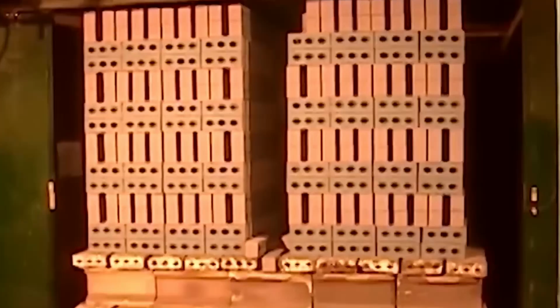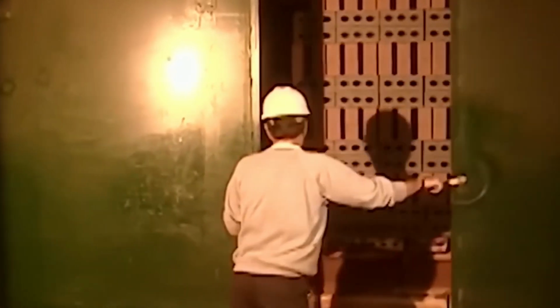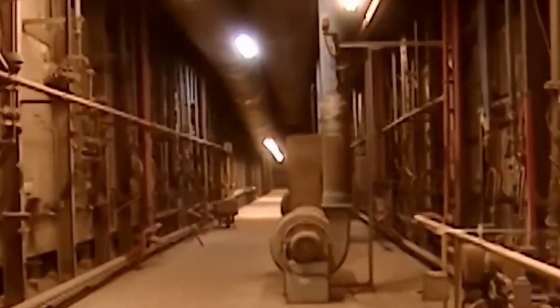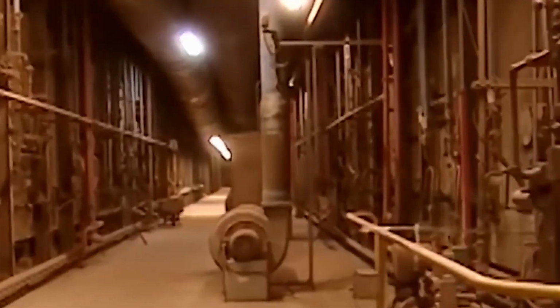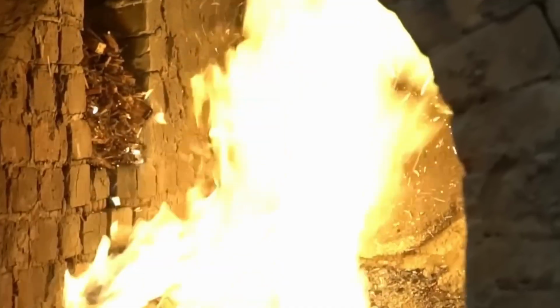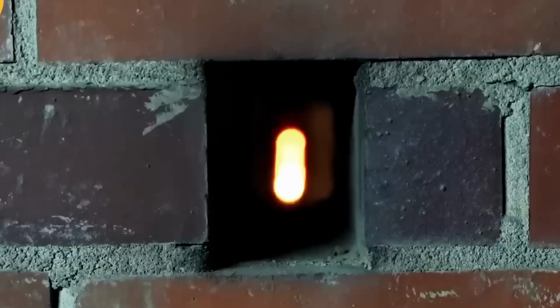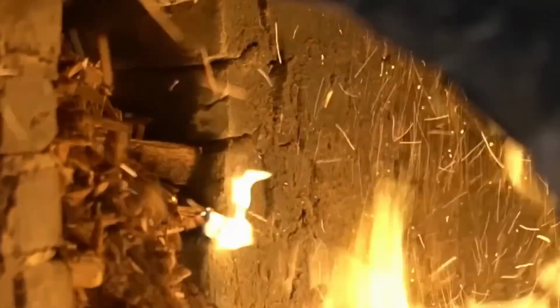The central zone of the kiln is the hottest. Depending on the type of brick and clay used, firing can reach temperatures close to 900, 1000, or even over 1100 degrees Celsius. At this temperature, the particles begin to sinter. This means they partially bond without completely fusing. Some components form a microscopic glassy phase that acts as an internal cement. This phase binds the grains, reduces porosity, and provides strength. The brick acquires its final hardness.